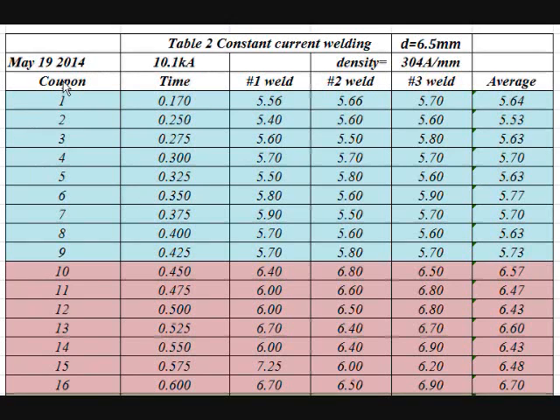This is experiment 2. It was performed May 19, 2014. This time the current is kept at about 10.1 kiloampere. The diameter of the caps is still 6.5 millimeter, and the current density is about 304 amps per square millimeter. And the first one that got a good size nugget is at 170 milliseconds.